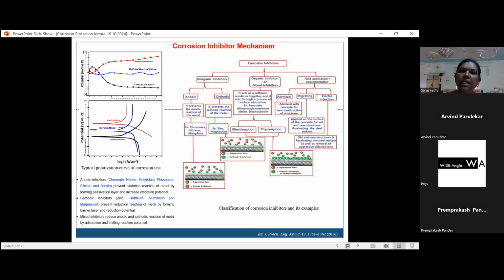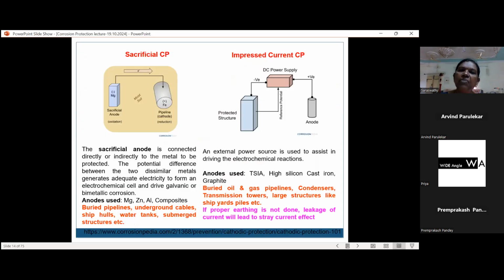For anodic inhibitors the mechanism is physisorption, and for cathodic inhibitors the mechanism is chemisorption. Physisorption means the film is physically adsorbed on the surface to protect the material, and chemisorption is chemically bonded with the material and protects the base metal. Again, sacrificial protection, the previous speaker has talked about it, but at CECRI we have developed sacrificial anodes for the protection of ship hulls, jetties and